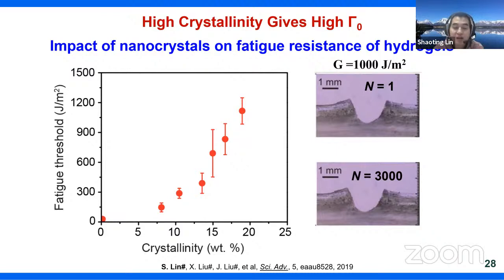Apply the same stretch level and do the cyclic loading. When the stress reaches a steady state, we can calculate the strain energy density stored in the sample. With that, we can plot the crack extension rate as a function of energy release rate. From that plot, when the energy release rate is low, the rate is 0, and when the energy release rate is high, it gradually increases. We use a linear extrapolation to identify this transition point. That threshold is the intrinsic fracture energy, or fatigue threshold, we identified from experiment.